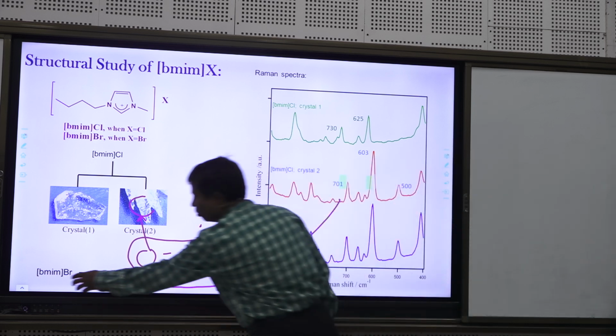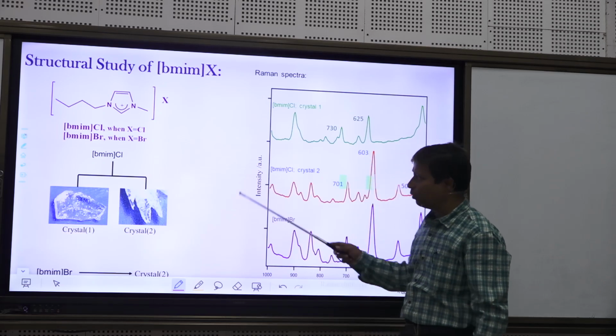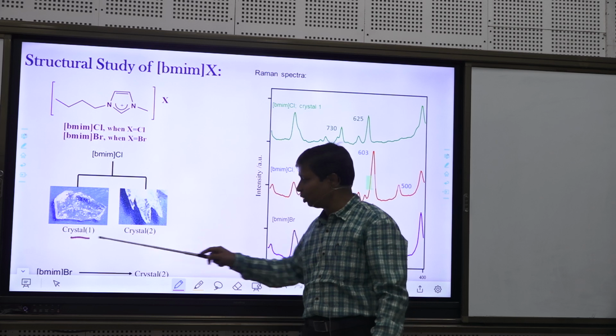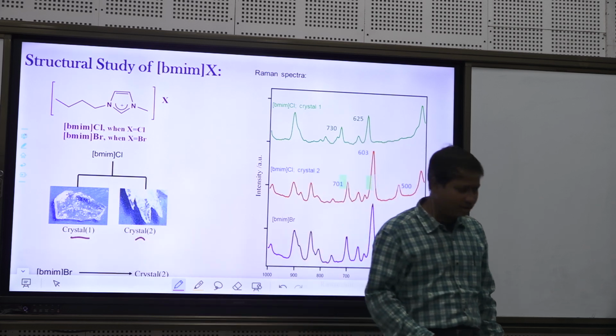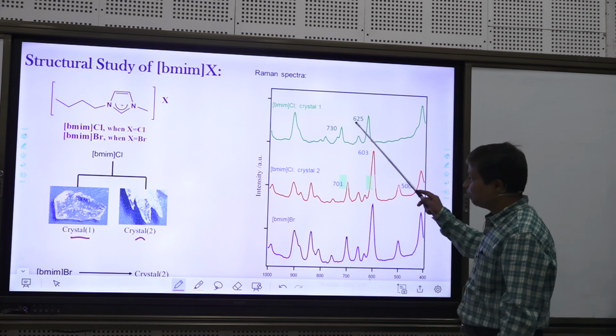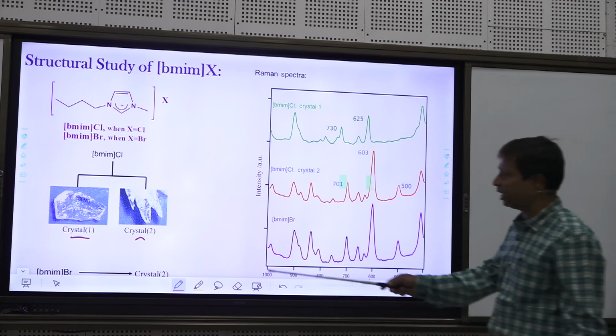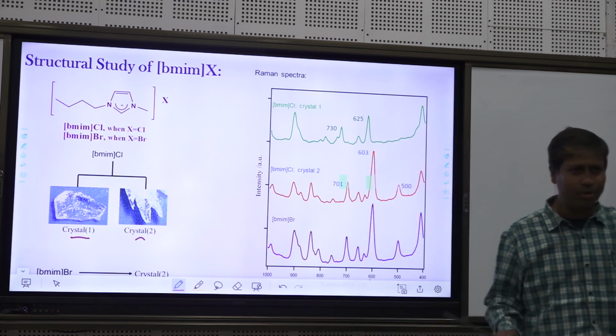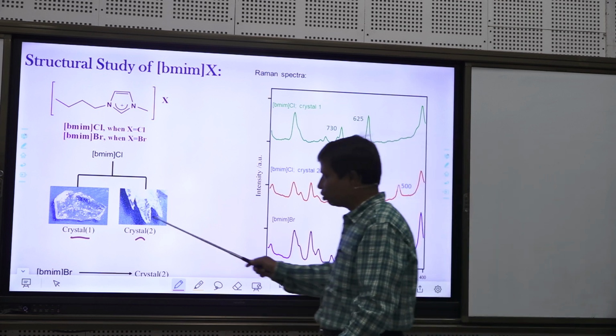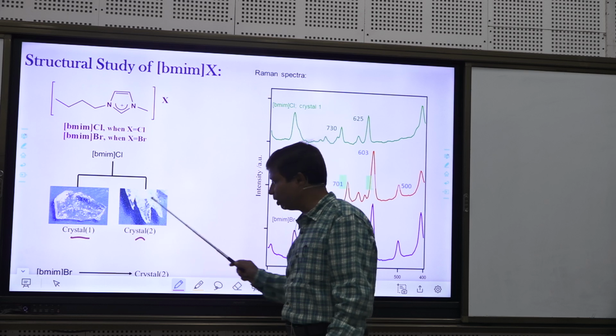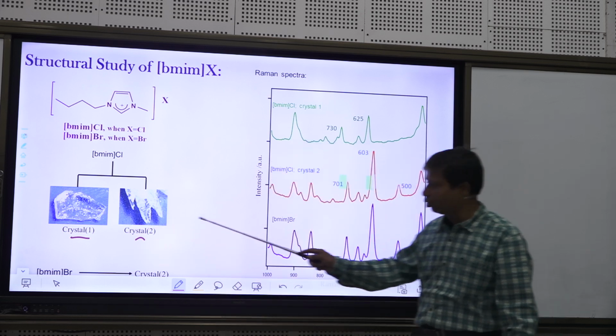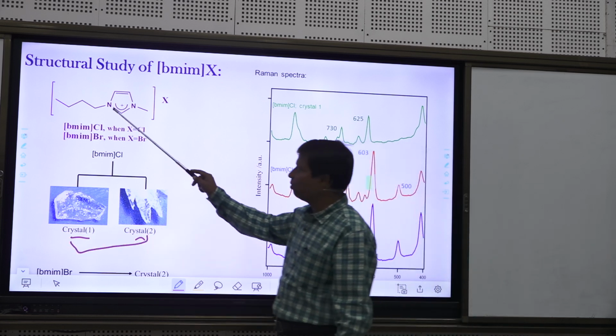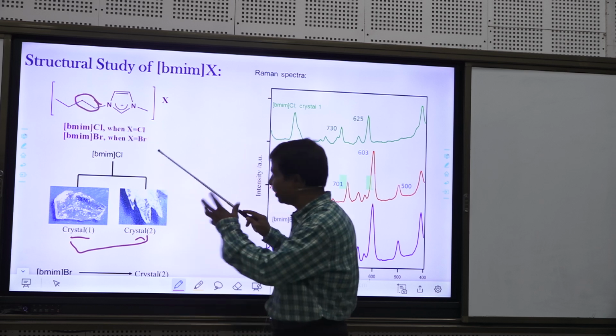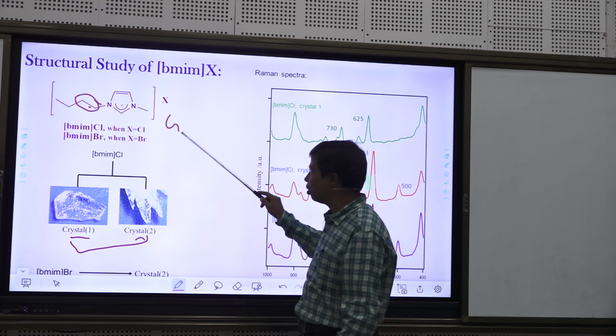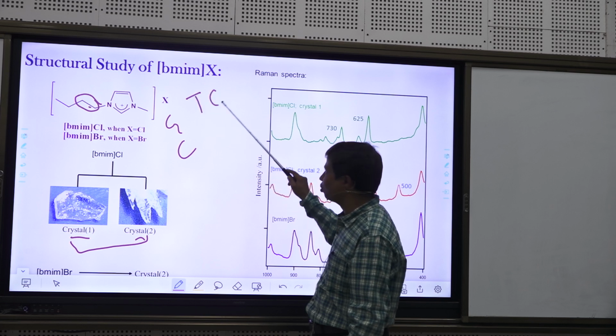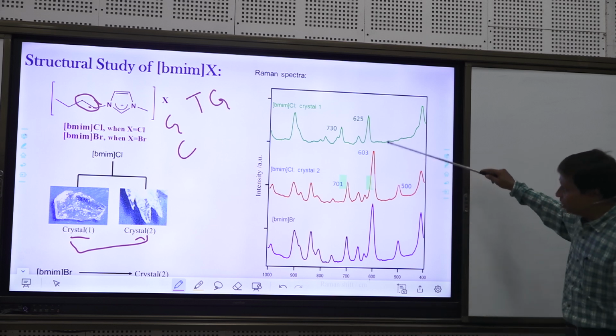So the story is like this. Last class I told you that once it happened that we were crystallizing this chloride and we found 2 different kinds of crystal. Later on we came to know this is a polymorph, and for that only Raman spectroscopy helped us, because these materials are very hygroscopic. You cannot take them out and put them in any other studies. So this one was done in a sealed cuvette, and then we slowly elucidated that these 2 are just polymorphs of one another, and this polymorphism is because of the cis-trans configuration, whether it is trans, gauche, or cis. So we found that trans and gauche conformation around this bond is responsible for the change in the Raman spectrum.